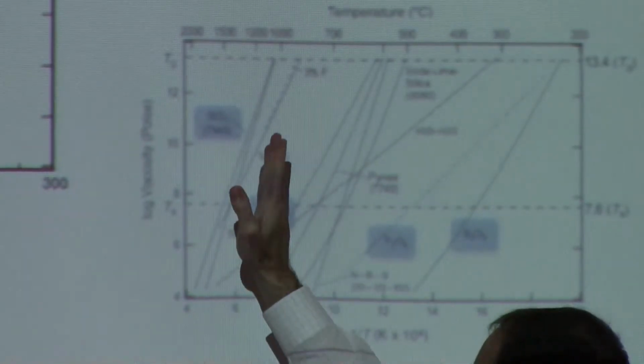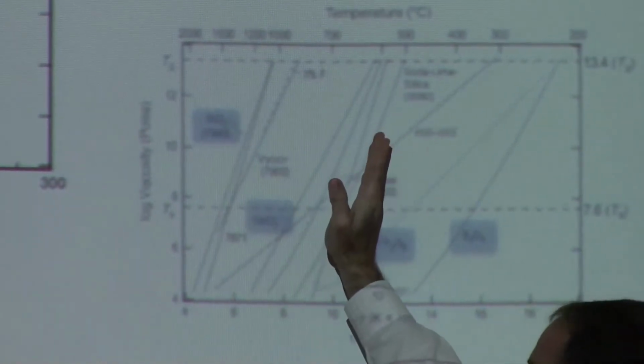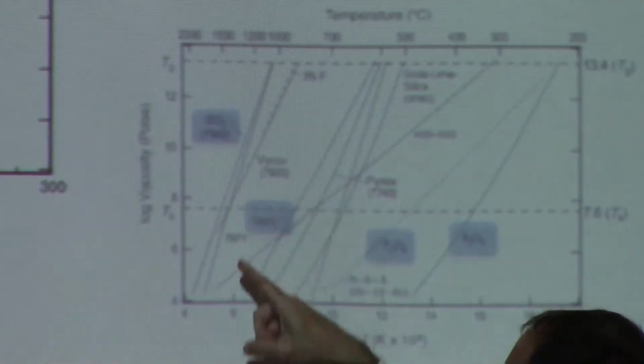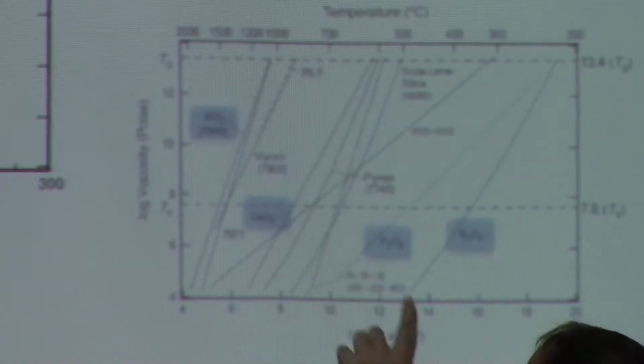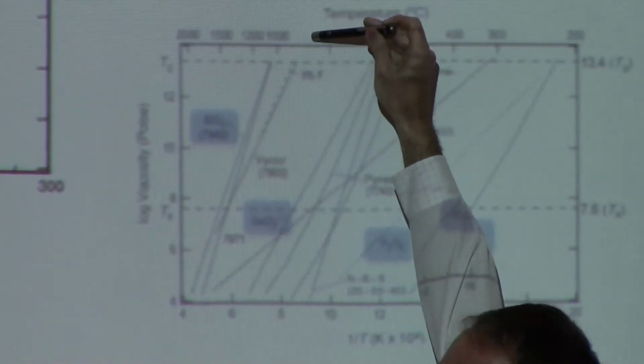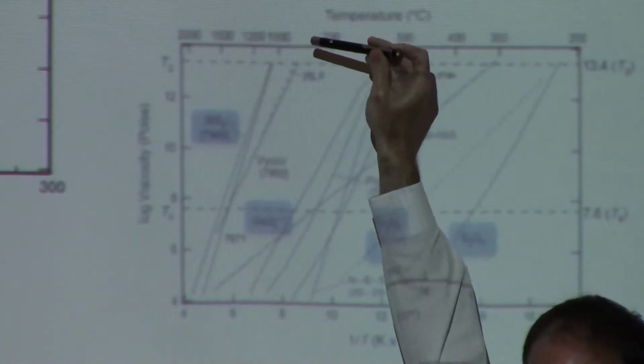right? So here's silica, beach sand. Here's normal lab glass, Pyrex. Okay, huge difference in viscosity for a given temperature, right? So this is viscosity, this is 1 over temperature. You pick your temperature. The viscosity is either here or it's way down here. You cannot co-process those glasses.